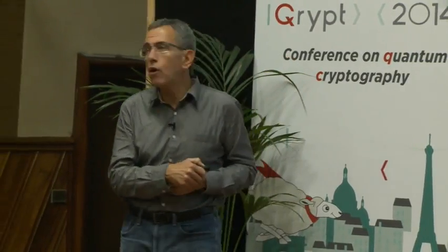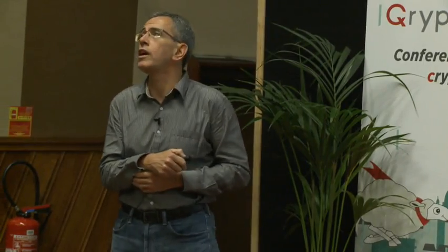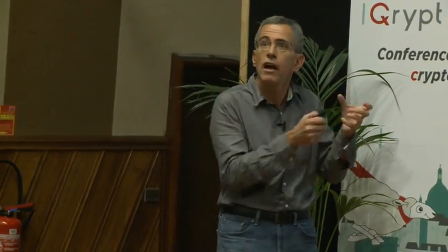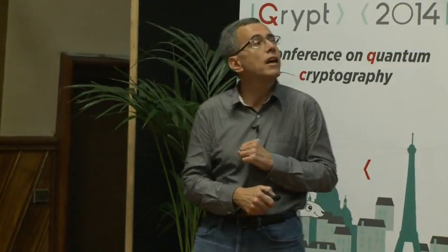So what we heard about yesterday are deep defects in solids. A good example is the NV center in diamond, but this is one example, and the community is now exploring other possibilities, silicon vacancy centers in diamond, as well as analogous vacancies in silicon carbide, which is a material that is easier to fabricate. The interesting thing here is that the properties of the emitter have nothing to do with diamond, nor the nitrogen or silicon that you have in there, because it is a deep defect.